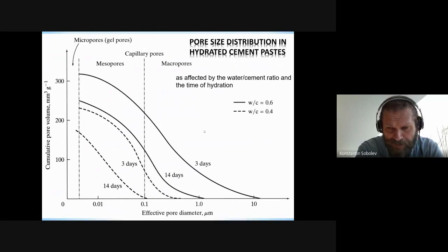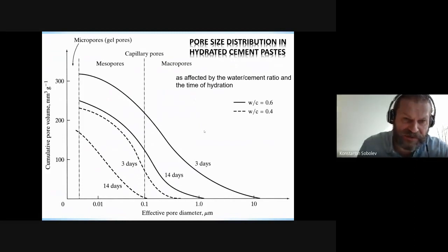Obviously, the effect of water to cement ratio was already discussed earlier today, and we need to understand also the effect of curing. Usually what we know about concrete in the lab is a material which is perfectly cured in laboratory conditions. What happens in the field, often we don't have adequate curing. And so you can see that curing is very important to formation of proper capillary structure and formation of mesopores rather than micropores, which are easily penetrable by fluids, and which cause the failure of material under environmental exposures.